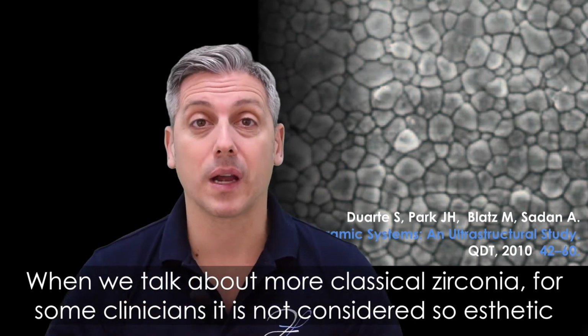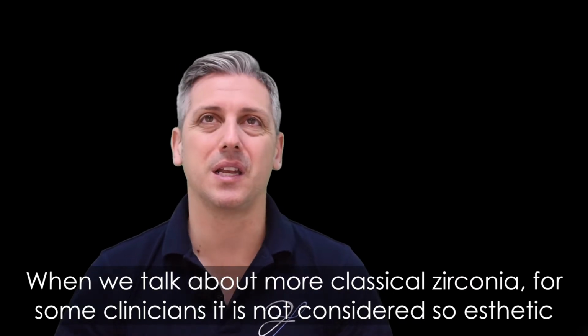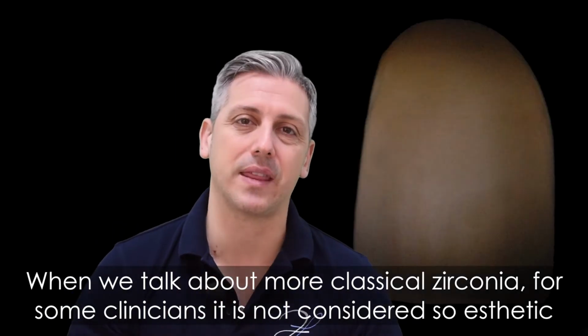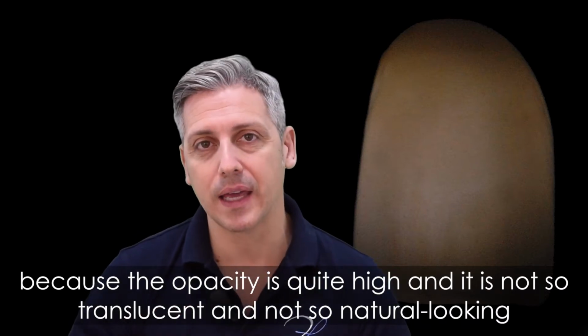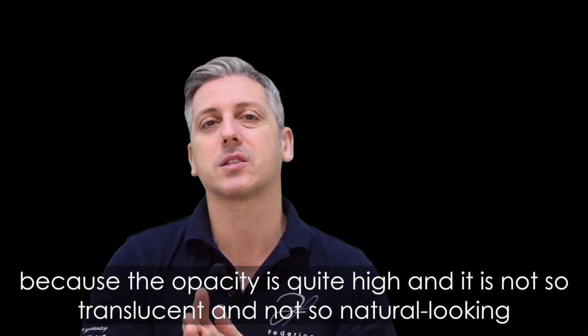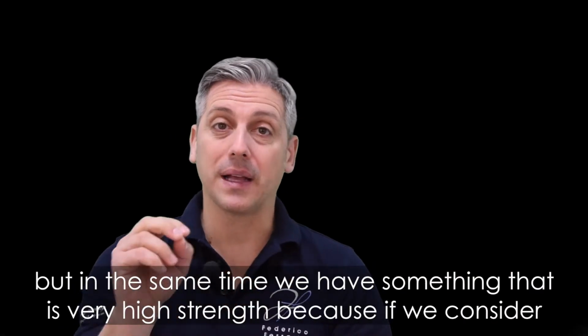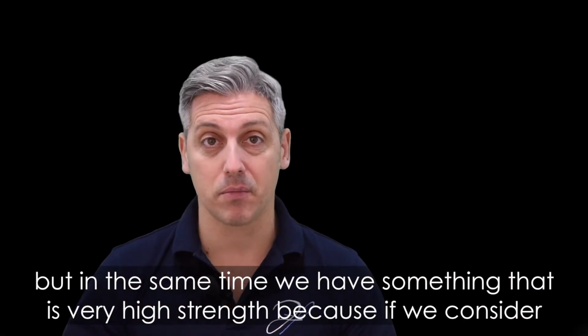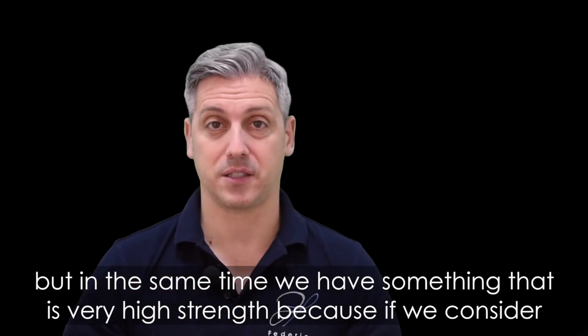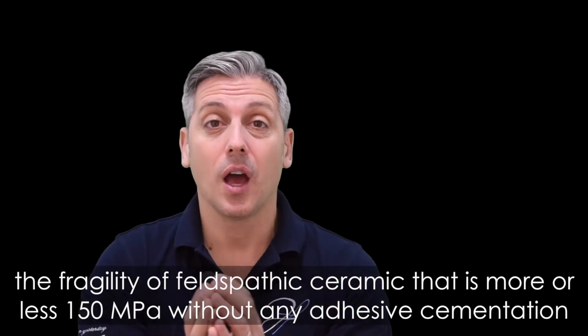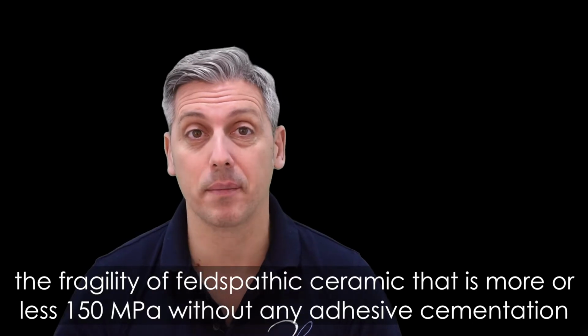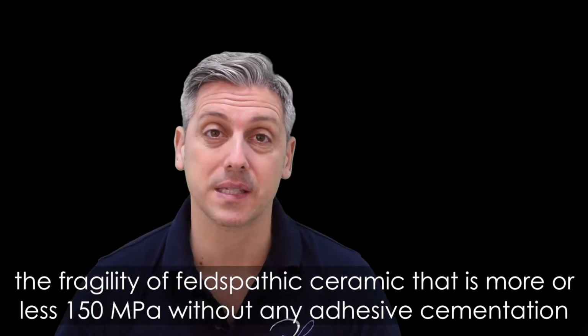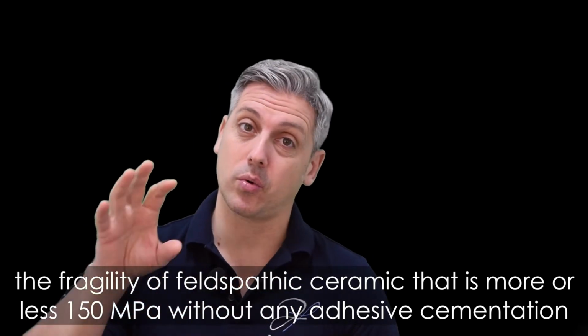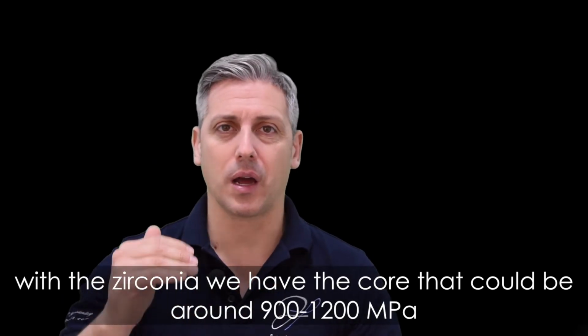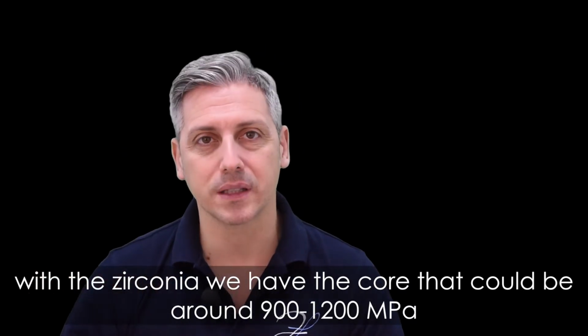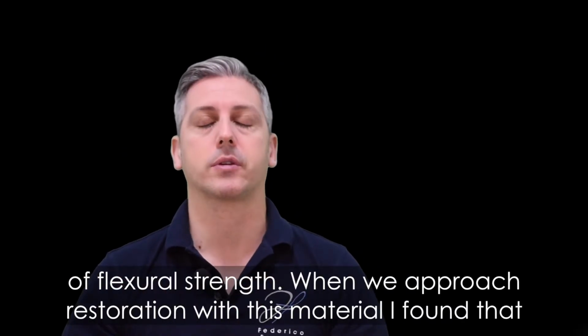When we talk about more classical zirconia, for some clinicians it's not considered so aesthetic because the opacity is quite high, and it's not so translucent and not so natural looking. But at the same time, we have very high strength. If we consider the fragility of feldspathic ceramic, which is more or less 150 megapascal without any cementation, with zirconia we have a core that could be around 900 or 1200 megapascal of flexural strength.